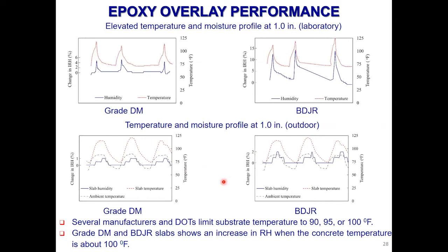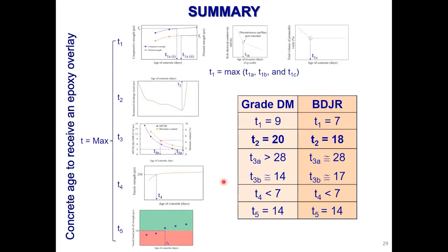And as I mentioned, I didn't include the results here, but we can see material softening with elevated temperature. So based on the parameters that we use for the evaluation to identify the concrete age to receive an epoxy overlay, when we look at all these, cracking age is going to control.